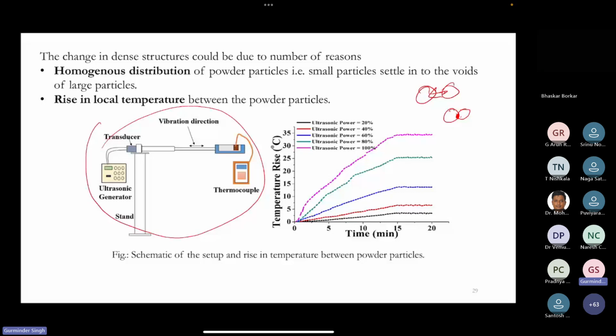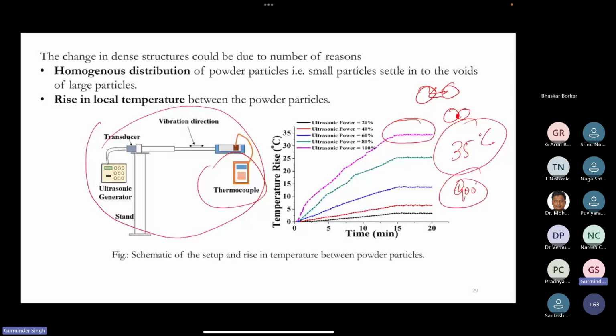So we have tested this using a thermocouple at room temperature, and we have seen at room temperature there was around a 35 degree rise in the temperature of the powder as compared to the room temperature, which is more effective at higher sintering temperatures. So if you are doing the sintering at 900 degrees Celsius, you will have around plus 50 or around plus 100 degrees Celsius energy at the local area of the powders.